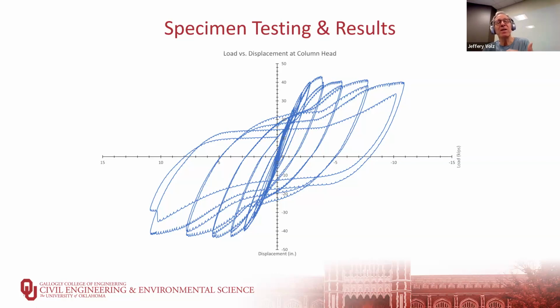But we're talking about putting very, very high strains on here, okay, up to 10%, right? We have an 8-foot tall column, so 96 inches, and going to a displacement of over 10 inches would give us over a 10% drift ratio or ductility factor. So it's very high displacement. But here we see we have a nice stable stress strain response, nice stable hysteresis loop, but then something funny happens in here. And you see in these later cycles, we have this dip.